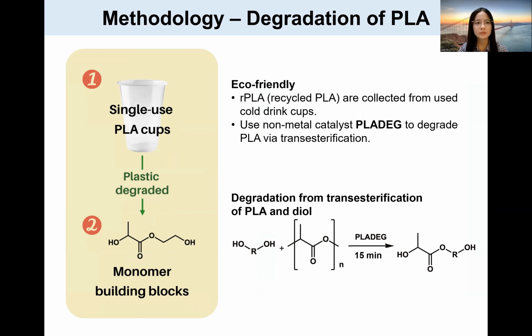PLA-DEG is a Lewis base non-metal catalyst, which promotes proton exchange and therefore speeds up the transesterification. How transesterification occurs is that the lone pair on the hydroxyl group will attack the carbon on this carbonyl group, and the electron transfer, and PLA-DEG can speed up the electron transfer process.